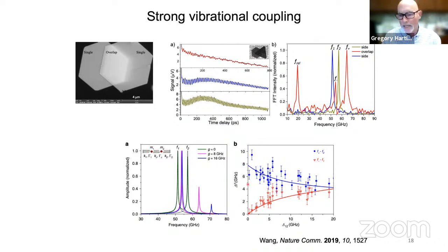If we look at the data down here, this is a plot of the shift in the frequencies for a whole bunch of different plates that have different initial vibrational frequencies. Delta 1,2 is the difference between the 2 initial frequencies. At this end, delta 1,2 being 0, we have 2 plates that have very similar frequencies. Over here, they have very different frequencies. If you look at the shifted frequencies, you see essentially an avoided crossing type effect. There are big shifts when the frequencies are close together, strong coupling, and when the frequencies are far apart, there are very small shifts. So this is a classic example of an avoided crossing in a 2-level system.